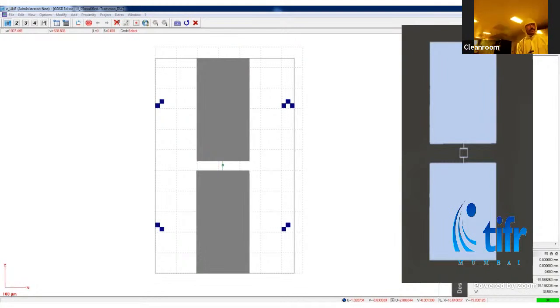And one thing to be noted is that this whole thing is going inside a vacuum. So the pressure maintained has to be around 10 to the power minus 9 to 10 to the power minus 10 millibar. Okay, and also for better resolution of our beam onto our sample, using these PCs we can manually adjust the focus and also correct the stigmation so that we get better resolution. And one advantage of electron beam lithography is that you can get very narrow resolutions, up to around 10 nanometers scale.